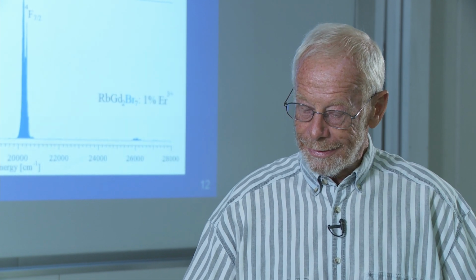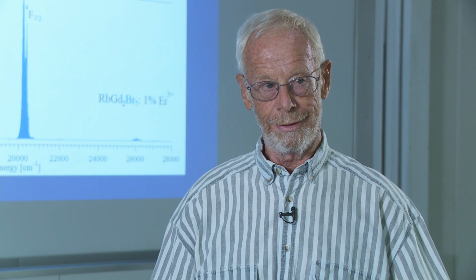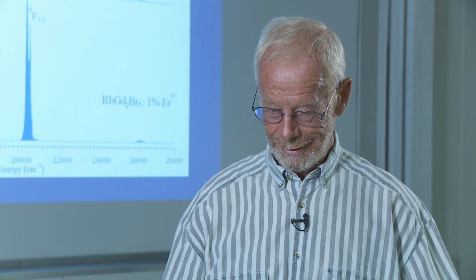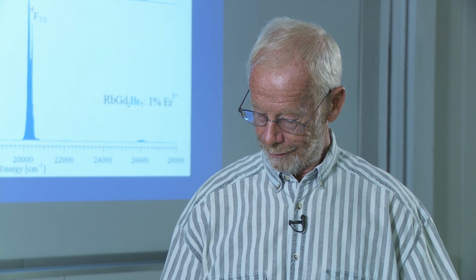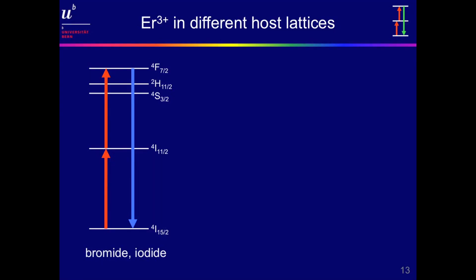And the nice thing with this one here is that we can explain the different color very easily. And I'm going through this very briefly. In a heavy halide, iodide, bromide, the phonon energies are small. After upconversion excitation, we get immediate blue emission.